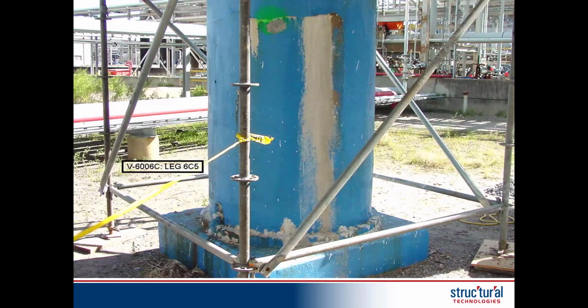That's when the moisture mixes and commingles with the calcium silicate hydrate, which is the glue that holds the concrete together. It emerges. It's calcium. If you were to taste that, I don't recommend it, but if you were, it'd be very tart. So it's salt-free lime. But what you don't see here is a lot of steel corrosion products, meaning rusting. That's telling us maybe we're early in the curve, but it definitely needs to be addressed, and that moisture is emanating from much higher in elevation.